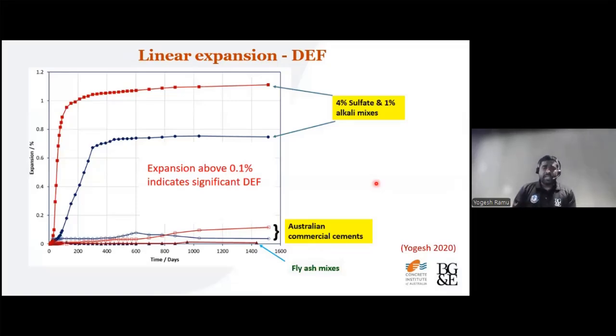So what we actually did is take the Australian GP cements and produce some laboratory mortar prisms and expose them to 90 degrees Celsius curing, and studied them for like 3-4 years. You can see the Australian commercial cements don't produce any significant expansion. In laboratory specimens, if there is an expansive DEF, it is precipitating and going to give some expansion in the length comparator study. So it doesn't have any expansion for Australian commercial cements.